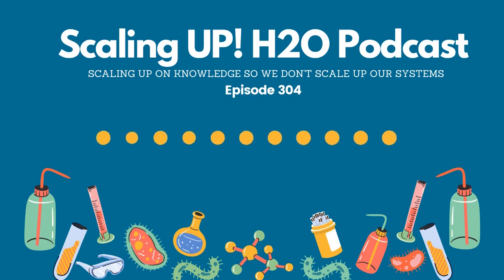And then there's a two-step cleaning process that we do. One, we've got to get all the organics off first. Now, the G1 standard that I mentioned earlier tells you how to do all of this. So we get all the organics off by putting a cleaner into the flask that we're using. We put that into an ultrasonic cleaner, and we add a certain amount of heat to it based on that standard for a certain amount of time based on that standard.